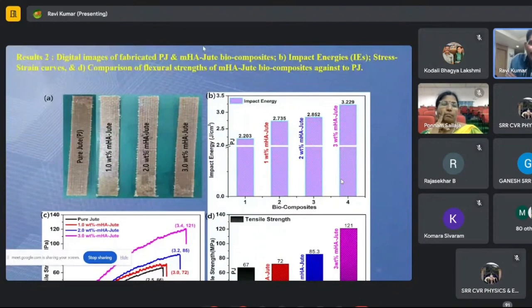And in the results, you can see the digital images of the fabricated pure jute, this one, and MHA jute with different weight%, like 1 weight%, 2 weight%, and 3 weight%. Also, you can see the biocomposites' impact energy. Impact energy means how strong or weak the panel is; we bombard it with a heavy weight, and whether it breaks or not is easily studied here. The impact test shows energy in joules per centimeter square. The impact energy for the pure jute is 2.2, but 1 weight% shows 2.7, 2 weight% is 2.8, and 3 weight% MHA jute shows 3.22. It is almost 1.5 times higher compared to the pure material. It means it is strong enough compared to the pure jute.